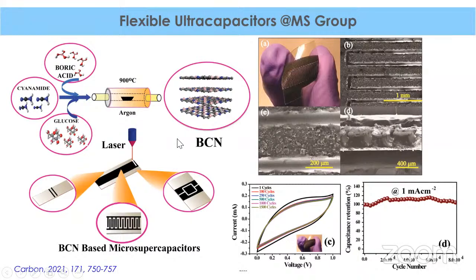So here, instead of redox molecules like RuO2 or polymer, he has used BCN, boron carbon nitride. Okay. So boron carbon nitride is basically where he has doped boron and nitrogen in a carbon matrix. So this boron carbon nitride is coated on a flexible ITO coated substrate, and here we have used a laser to make such interdigitated electrodes. We call them planar micro supercapacitors.